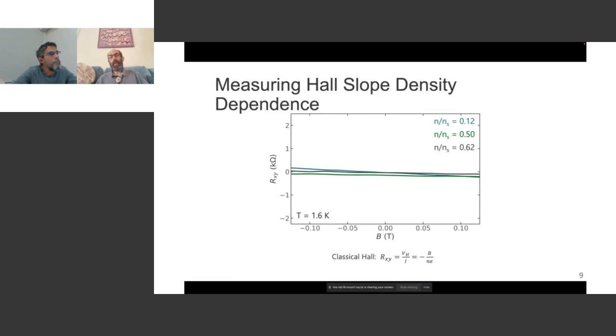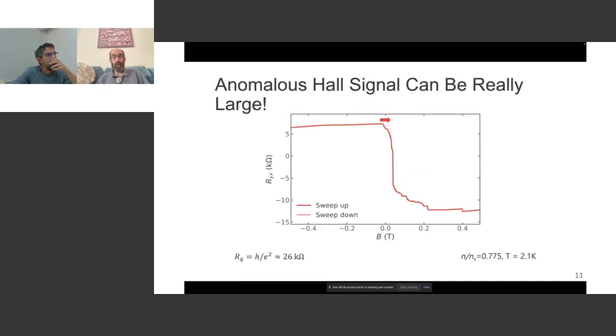But then at 3 electrons per moiré cell, it looks a bit different. In fact, dramatically different. The Hall slope is quite large, even at very low magnetic fields, and it's no longer linear. It saturates at these low fields. And so that was really quite striking and surprising. And so Aaron decided to cool this down in a fancier cryostat that could go to lower temperatures. And here's what he saw.